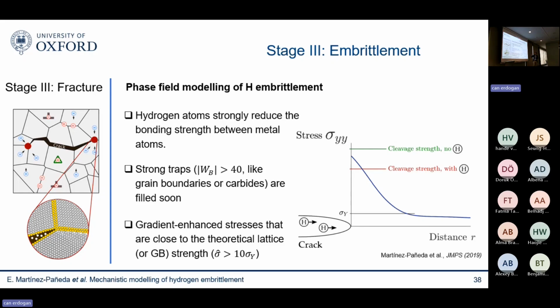But what we see is that when we account for those GND effects that I mentioned before, for those plastic strain gradients, your hydrogen content is big enough and your stresses are big enough that this cleavage strength, which you don't reach normally in the absence of hydrogen, hence why you need the ductile micro-void mechanisms, is lowered. Your stresses cross, these two lines cross, and then you have fracture. You have a model that, just by running one atomistic simulation offline without any fitting coefficients, is able to naturally predict the shift from ductile to brittle.